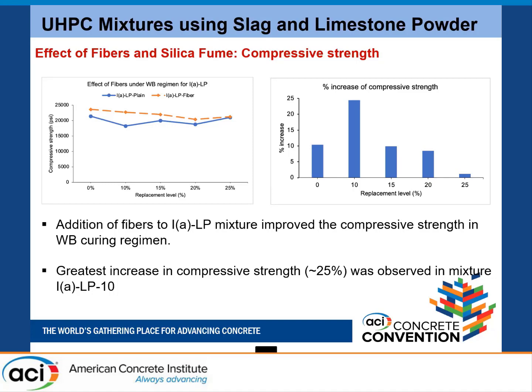The percentage increase in compressive strength along with silica presence varies with replacement level. If you see, the greatest compressive strength we achieved was at the 10% replacement level of limestone powder when compared to others, but still 15% is a viable option because we are able to produce more than 17,000 psi compressive strengths.